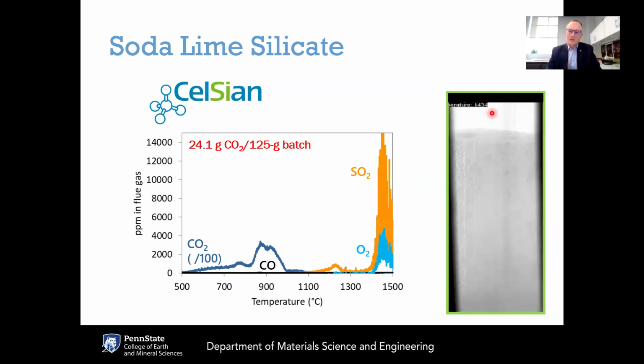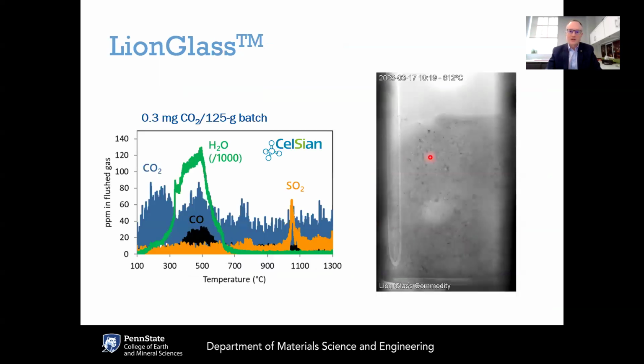And as we get to 1400 degrees C and a bit above that, you can see this foaming behavior. And then when we get closer to 1500 degrees C, things calm down. And then at that point, we get a nice, well-fined, homogeneous liquid. But it does require those high temperatures to get good quality melting in soda lime.